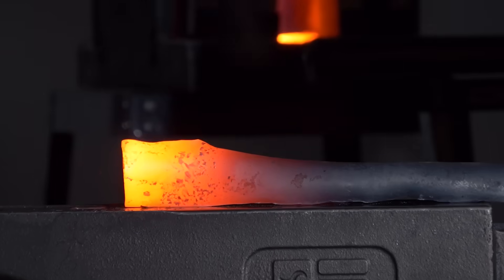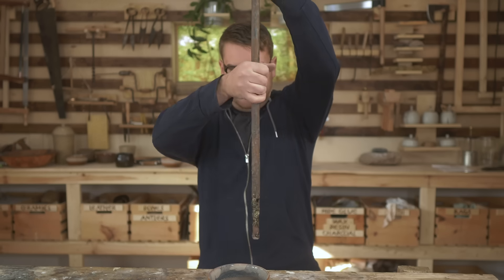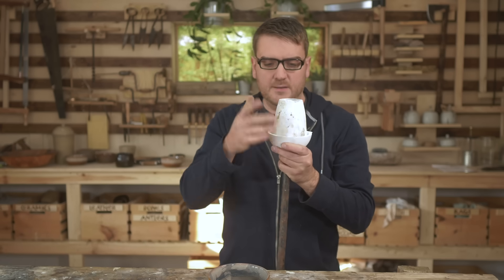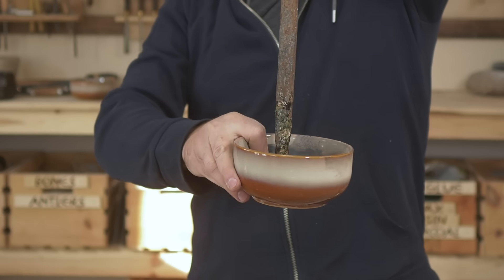I have a piece of crucible here and a blowpipe for glass blowing that I'm going to repurpose for this. There's a hole that'll fit the pipe, going to have a top like that. And then below, it'll sit inside a bowl of water. It'll heat up, turn into a gas, and be unable to escape out of the crucible. So it will go down through the tube into the water, which will then cool it as a solid metal.